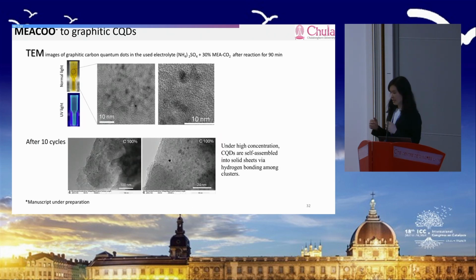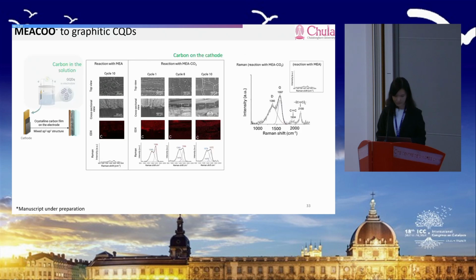It's actually just obvious from the TEM images. The presence of the graphitic carbon quantum dots with a size around 3 to 5 nanometers can be seen just from TEM images. If we have high concentration, they can merge and form the graphene sheet, let's say. That's our carbon in the electrolytes.